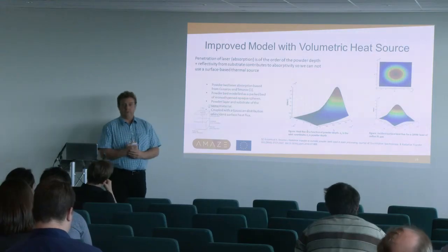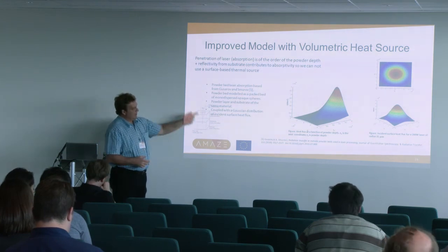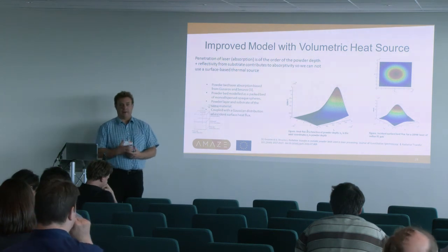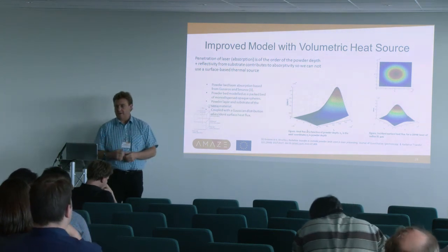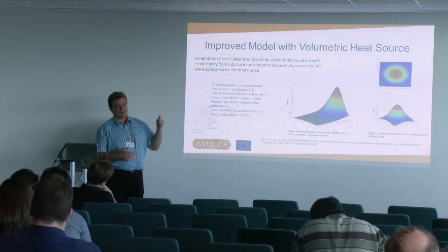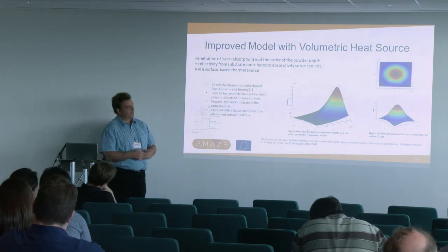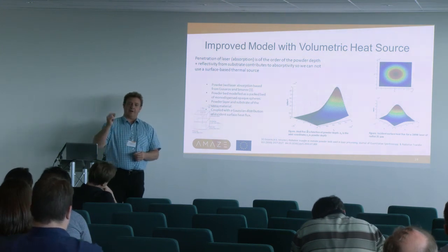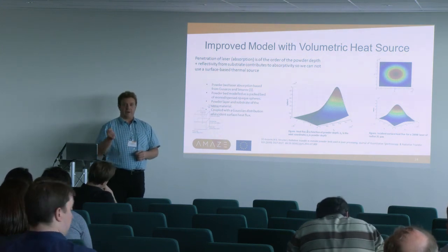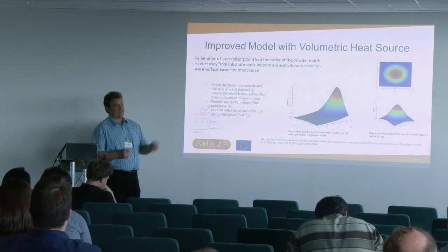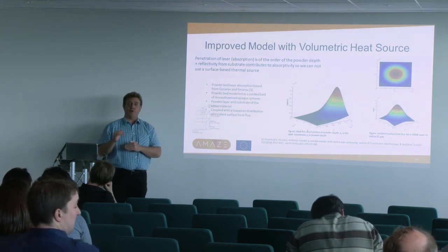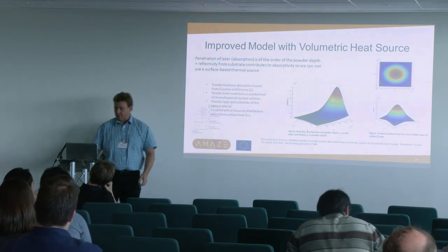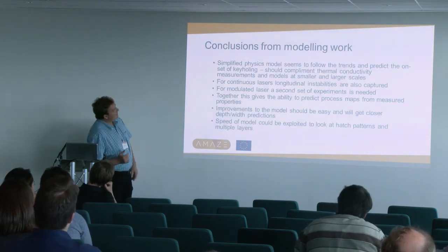We need to improve the model. The way the laser penetrates through the powder was not obvious to us at the beginning, but that's become more obvious now. The Russians already knew it a while back, and they've got some equations which suggest that in titanium 6-4, the penetration of an optical laser like this into a powder bed is of the order of the powder bed thickness. So it can't be ignored. You can't just assume you've got a heat source on the top. So that's it, really.